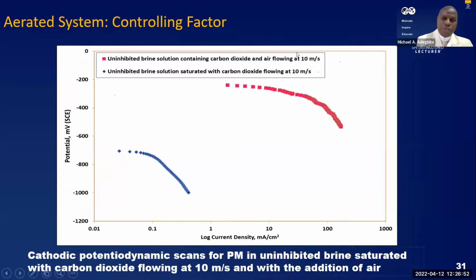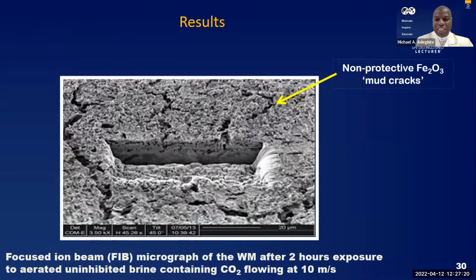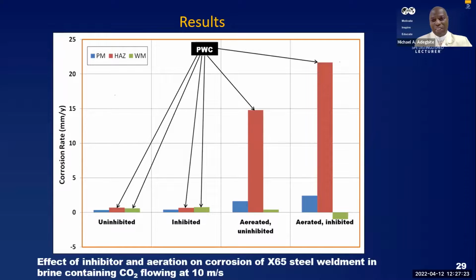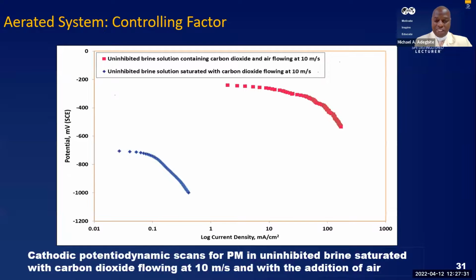This is what we have when the air is admitted. That's red, and without air is the blue. This is a log current density, so we can see an order of 3. The corrosion rate is increased by a third order, and that's a phenomenon. It also corroborates the results that we've also seen in this particular graph. That is the spike in the corrosion rate compared with when there is no air in the system.